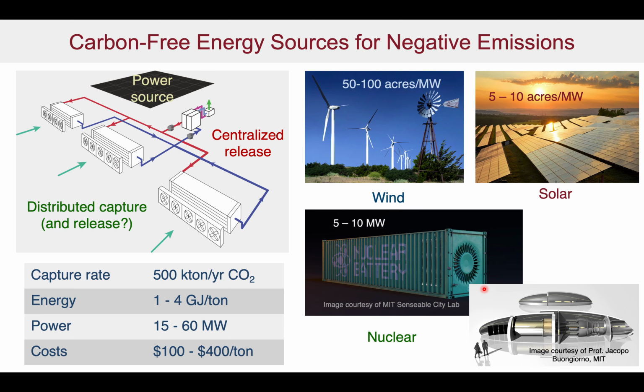So where does all this energy come from? Well, we need carbon-free energy sources for negative emissions. We can rely on a distributed capture and release, or a centralized release in which we capture all the CO2 in a solution and then just release it all at a centralized location. The capture rates would be on the order of 500 kilotons per year of CO2, the energy about 1 to 4 gigajoules per ton, and the power would be about 15 to 60 megawatts. And this brings us to what kind of sources do we need?